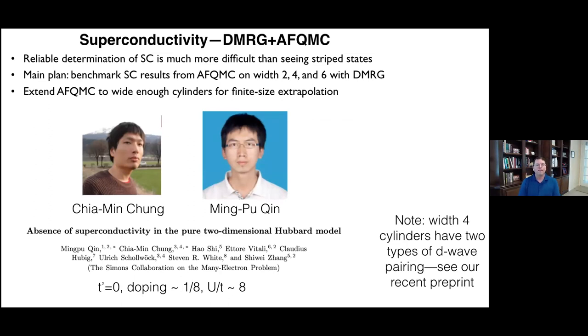Figuring out what the superconductivity does in more detail is more difficult than seeing the stripe states. And so we tried to focus even harder, combining these two methods, validating the quantum Monte Carlo with its constraint on the widest accurate ladders we could do with DMRG, and then extending the Monte Carlo to wide enough ladders for finite size extrapolation. The conclusion was that at this particular point, we could extrapolate to the two-dimensional limit and find an absence of superconductivity. And this is in the pure two-dimensional model, meaning without any t prime, just t prime equals zero.